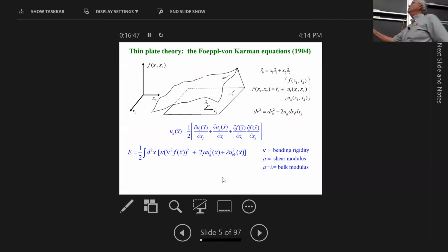It goes back to 1904, and it leads to something called the Foeppl-von Karman equations. These were two very distinguished scientists working on the physics of thin sheets. And the idea is if you have a thin elastic sheet, of course, there are atoms and molecules that make it up. But one way to think about it when it's allowed to escape into the third dimension is to say there's some background flat sheet that's shown down here. That's this thing R0 that's parameterized as a function of x1 and x2. And then the phonons, the excitations, are in-plane phonons, the usual in-plane phonons that you might encounter in a solid state physics course. And then there are these out-of-plane modes that allow it to go into the third dimension.